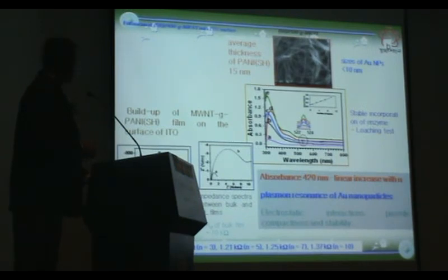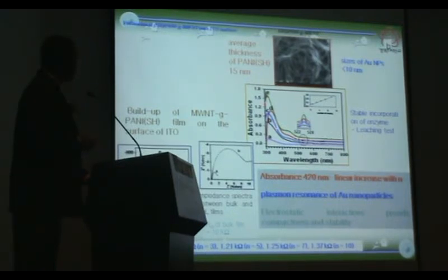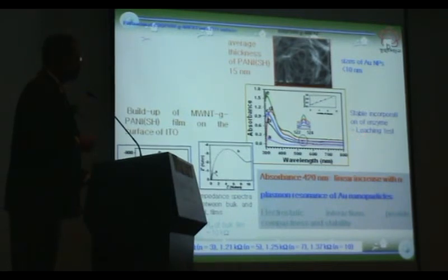The compactness was checked by following the optical absorbance in these two regions. There is a gradual increase in the absorbance value corresponding to the polymer, and a gradual increase in the absorbance value corresponding to the plasmon resonance of the gold. So we also tested the linearity of the increasing absorbance in terms of the number of layers. When the number of layers increases, the amount of gold nanoparticle can increase, the amount of polymer can increase.